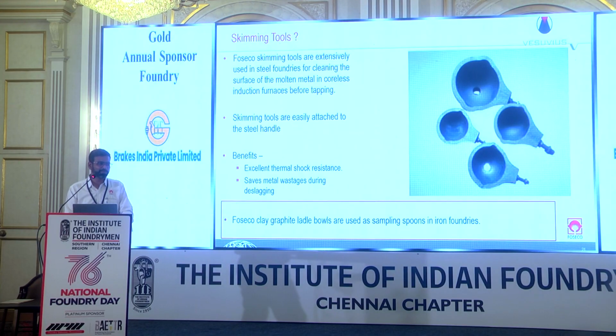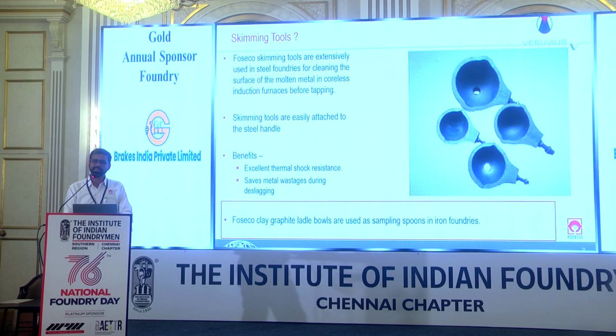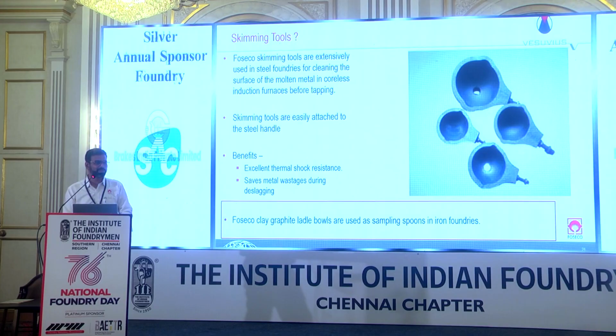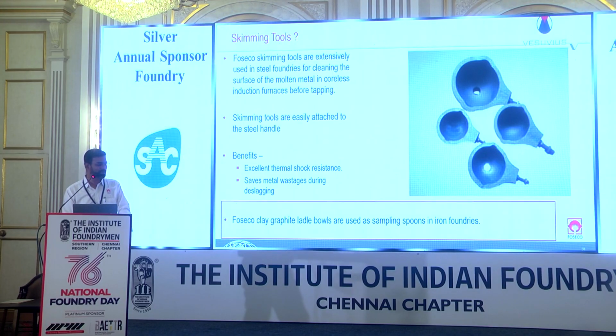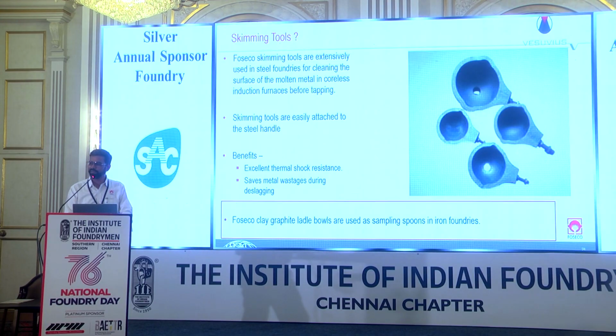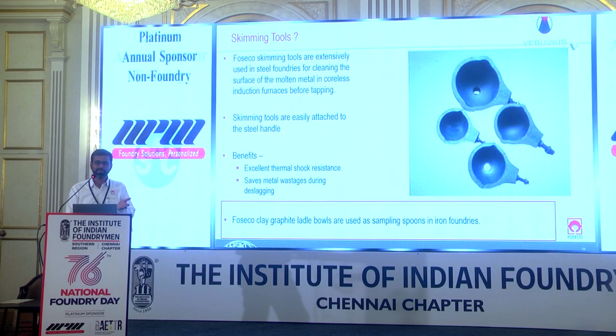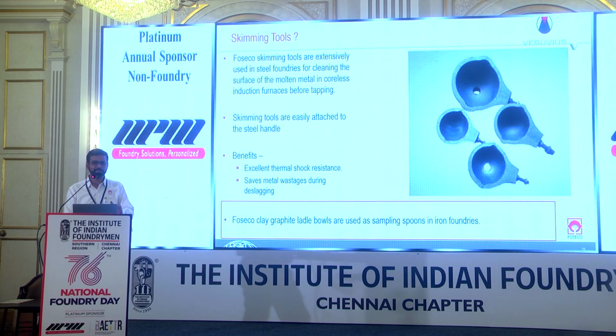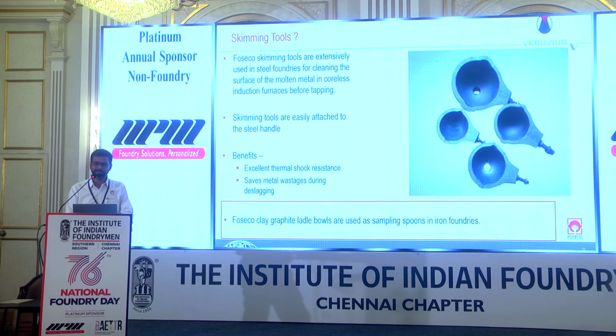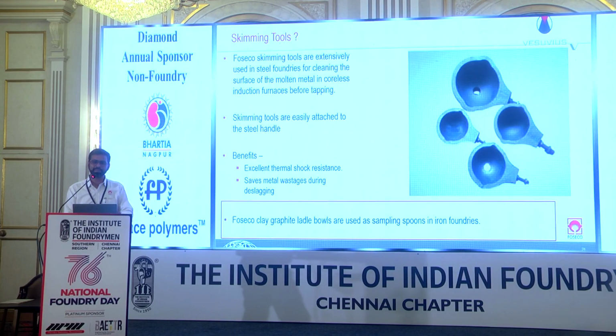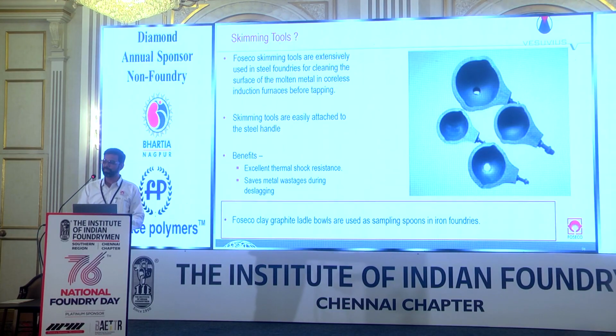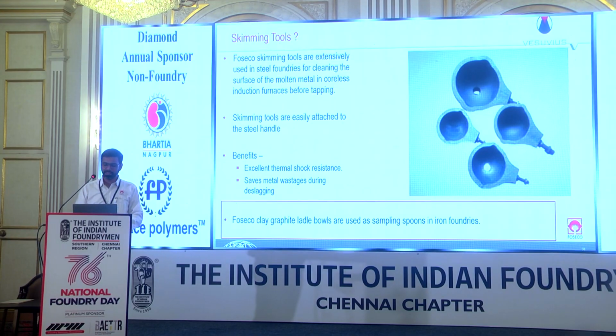Some of the foundries, I know, have started using this type of tool, which is very effective. They allow very minimum contamination of metal with slag. So it has holes from where metal will remain in the furnace, and only slag will come, and that is how the metal recovery itself is higher. The slag collected in the bins is mostly in oxide form only, so very little metal is in that.